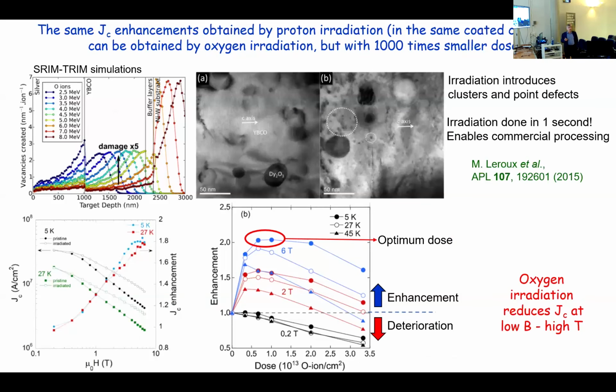Then we did the same kind of irradiation, but with oxygen ions instead of protons. The reason for that is that we could obtain similar damage, measured in DPA, displacements per atom, with 1,000 times lower doses than with the protons. So these irradiations were done in 1 second, for instance. We argue that could be useful for technological applications. So you can see here, I will not go into the detail, these are SRIM-TRIM simulations.